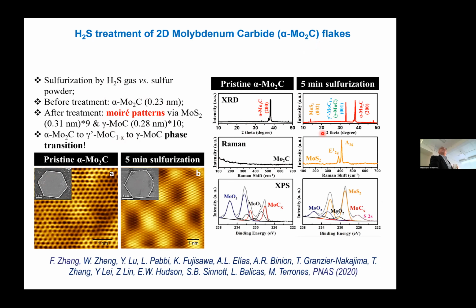And then after 5 minutes of sulfurization, we could start seeing molydisulfide, and we can see it clearly in all these characterizations. So in this case, we're growing molydisulfide on top of the molycarbide.